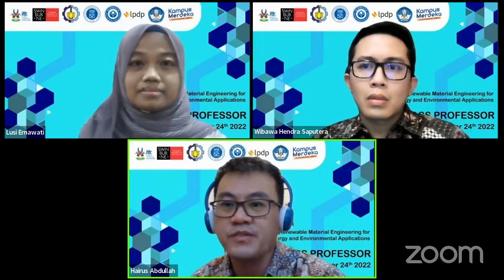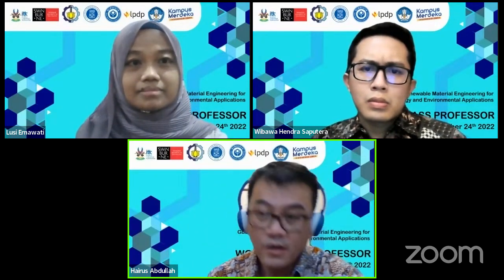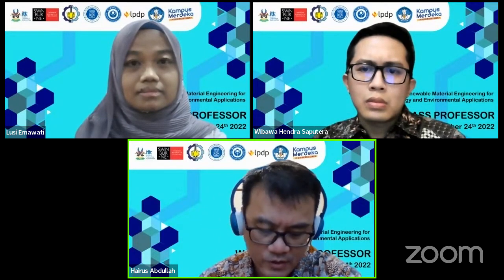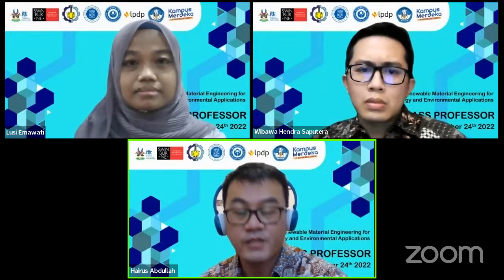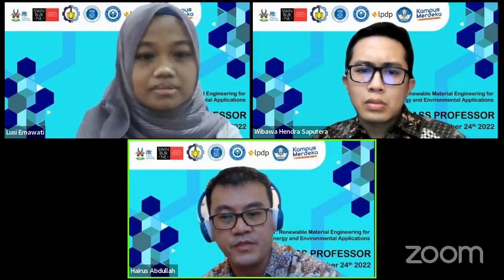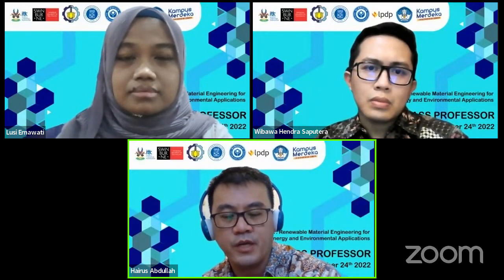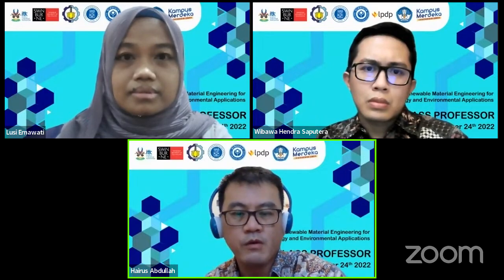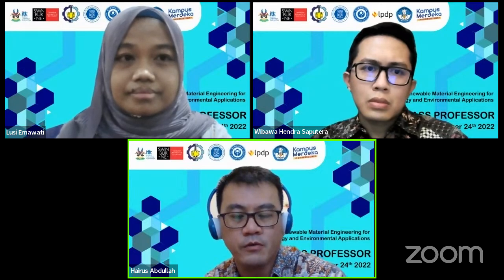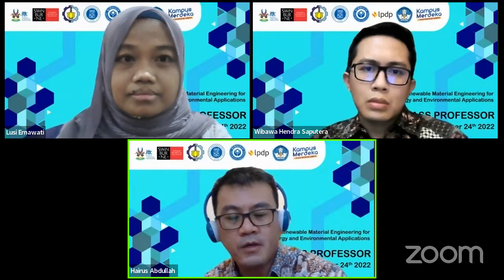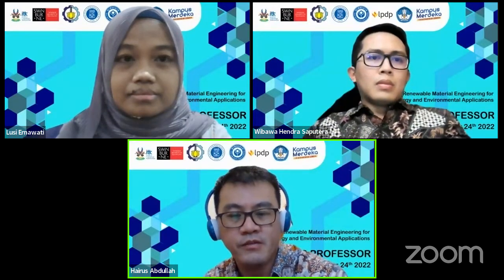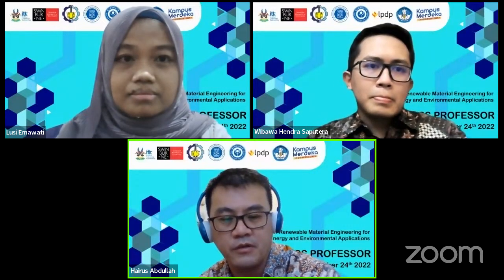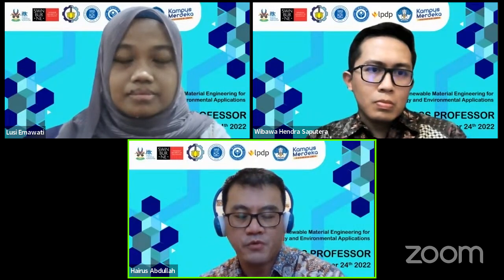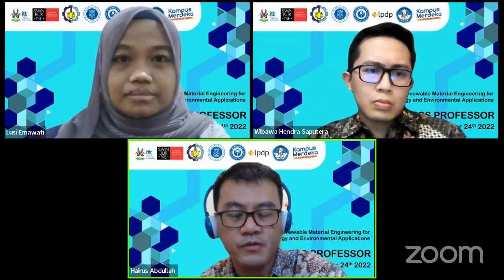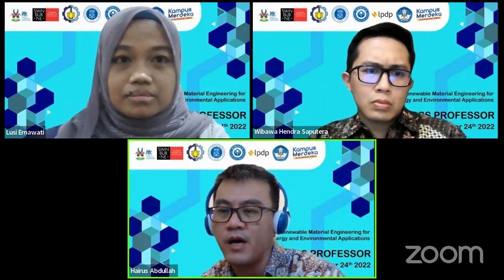So maybe at first, Dr. Hairus. Okay, thank you very much for the questions from Ms. Rizka Lestari. I think why the LH mechanism is preferred in the photocatalysis reaction, as I observed from some papers, is because of the adsorption at the same site. When the photocatalytic reaction happens, the first step is the adsorption. Without adsorption, the chemical species cannot be degraded because there is no charge transfer. In this case, the site of the photocatalyst for the adsorption and the reaction site are the same place, right? So there is a rate determining step, because the species should be adsorbed first, then after that we have the reaction, then it will detach from the surface of the catalyst. So that's why you will follow the LH mechanism.